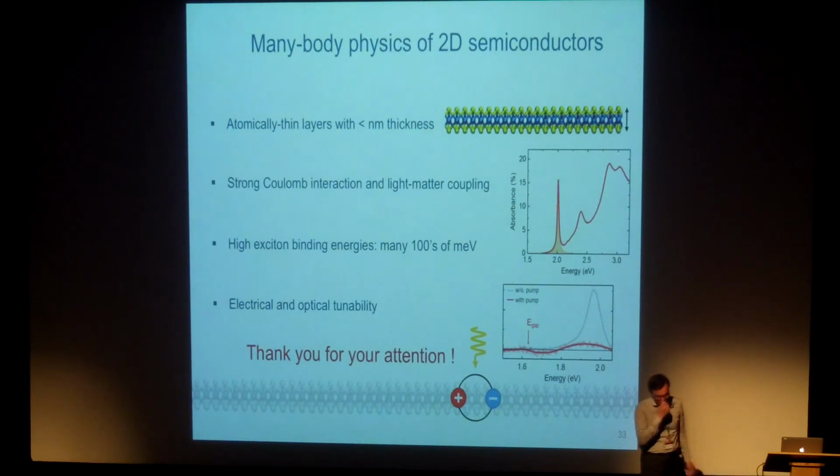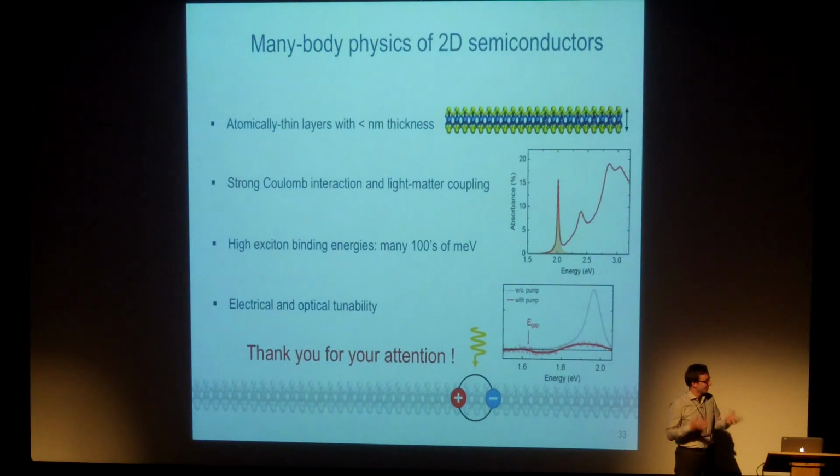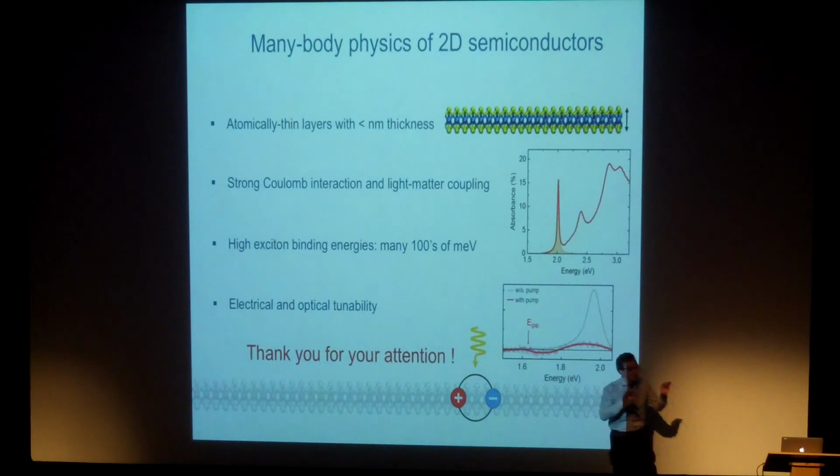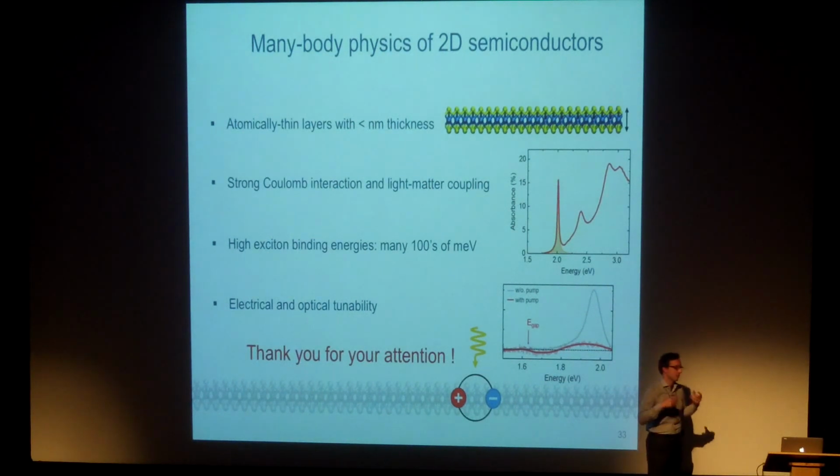Okay, so first of all, I was maybe somewhat misunderstood in my representation. I said the heat of the electronic system is very high, and that will cool down within a few picoseconds, usually by emission of phonons, not into the substrate yet. It will still be in the layer. The coupling to the substrate is such that if one measures this interfacial heat conductance, and there are a few ways to measure it, you get a few hundreds of picoseconds for usual transfer times.